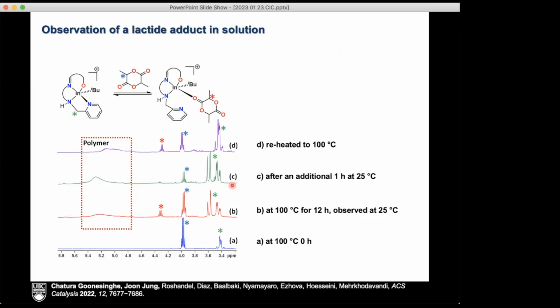So what Chatura was able to observe was actually the NMR spectrum of a lactide molecule coordinated to indium in this system. What he was able to show is he has the system at 100 degrees. You can see that there is a peak here for lactide after taking this and heating it in lactide for 12 hours. We can actually see a new species, which is this one, coordinating to the indium center. If you bring it back down to room temperature, it's gone. If you reheat it, it shows back up.